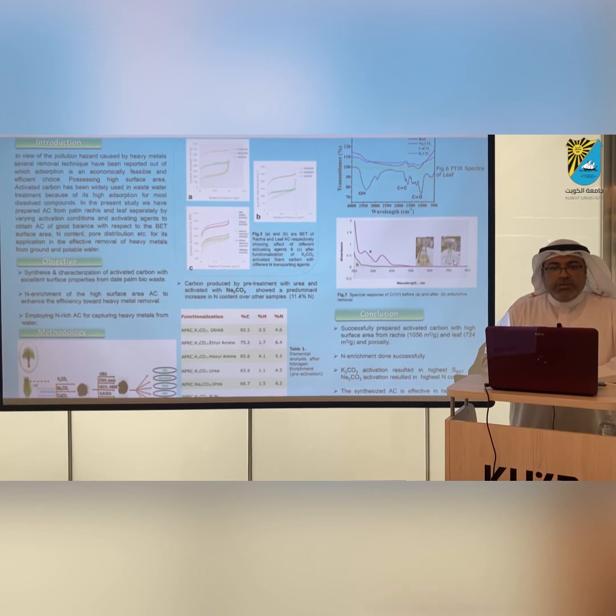And this way we will save time. We think we can reach 15 or 20 minutes by designing this. And then we can recycle the nitrogen, cool it down, and send it back to the activated carbon to reduce also the time needed for cooling, because as I told you before, the cooling also needs time. We need to reduce both the heating and cooling time. And thank you very much for listening.